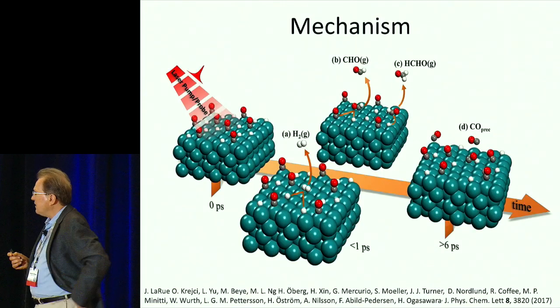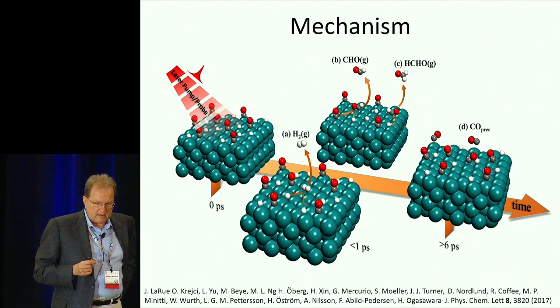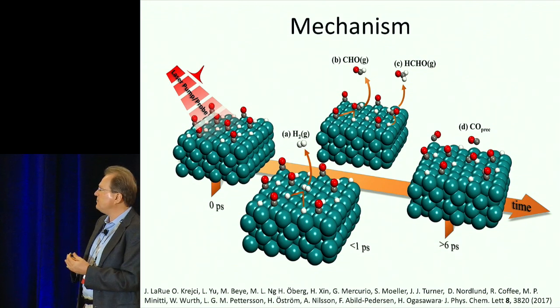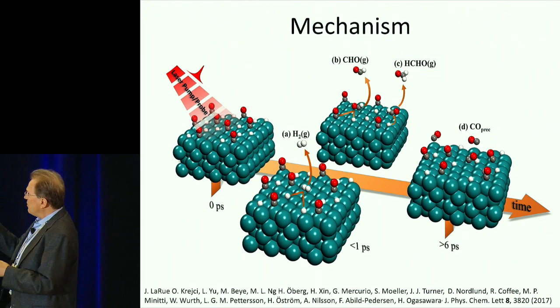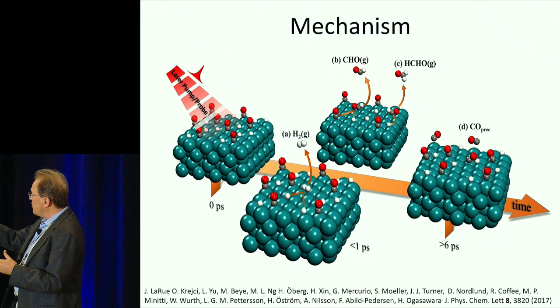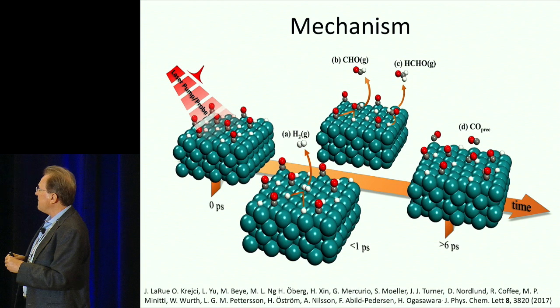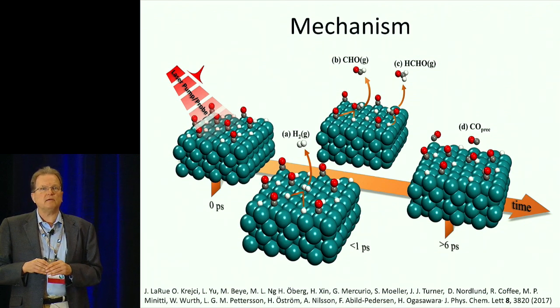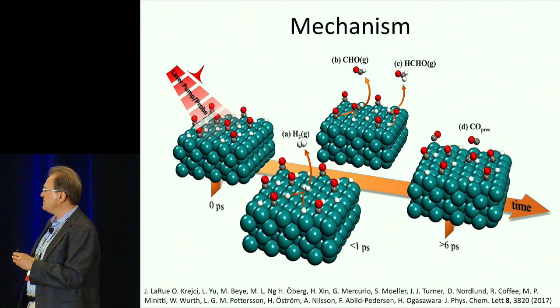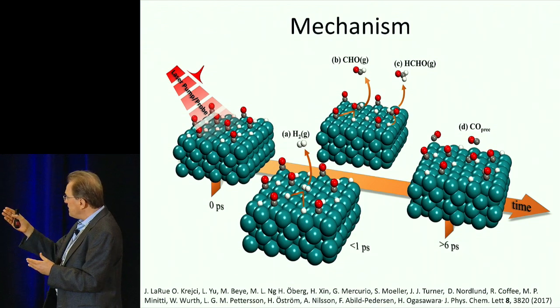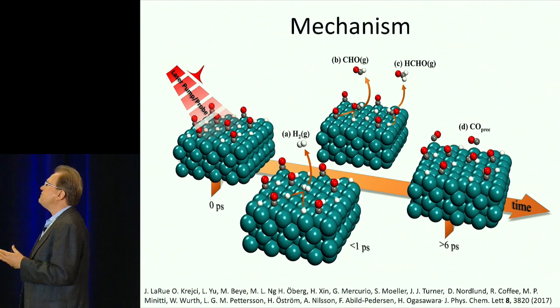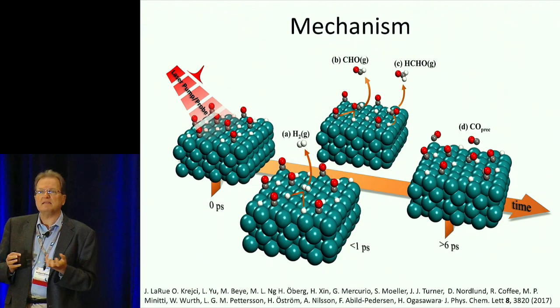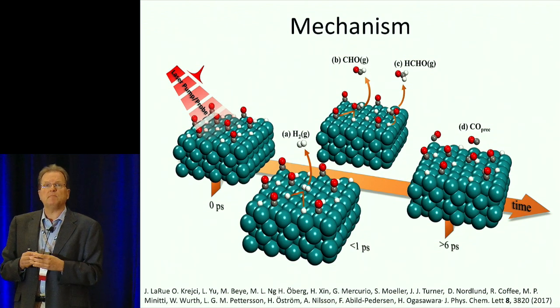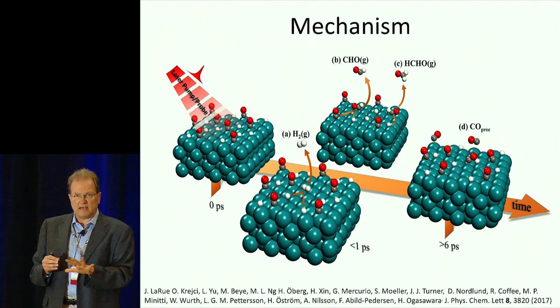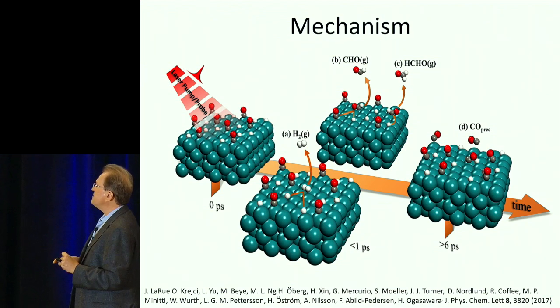And we can derive a mechanistic picture here with different time scales. We can think about chemistry a little bit in different time scales, because on the left there it's CO plus H. As time goes on, along an axis here towards the right, you have on the upper part there the CHO being formed. But on the lower part, you also have a competing mechanism, which is hydrogen being desorbed from the surface. And these are competing with each other. And eventually, on much longer time scales that we have measured in a different experiment, which I didn't speak about, we can see CO leaving the surface, being trapped in another metastable state called the precursor state, sitting just outside the surface. So we can follow all this now in real time.